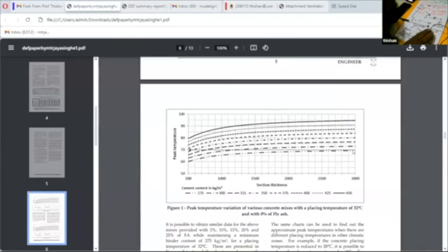275. Anything above, you can see temperature goes above 70, and you are not in a position to make the concrete really cool, because it's a very long concrete pour. So even if you start midnight, you might have to finish it throughout the following day. So you have no control over the temperature.